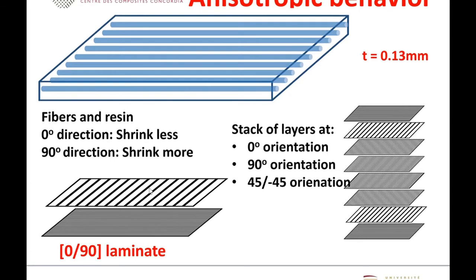At the same time, you take a look into the second layer, the layer above, which is at 90 degree orientation. So along this way, you can see that it expands and contracts a lot along the so-called X direction, but it expands and contracts very little along the Y direction. So when you put these 2 layers together, they bond together to make a single unit. Then when you either heat or cool it down, the difference in the degree of shrinkage or contraction along this direction, and the interaction between these 2 layers, will make it curve. So in this case, you can make a curved structure from a flat mold.